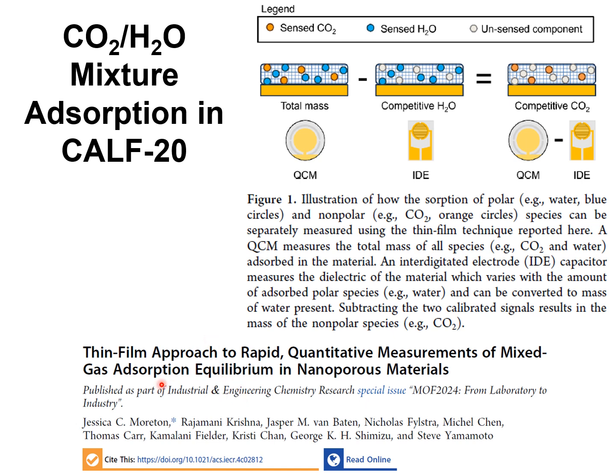This development is reported in the paper titled Thin Film Approach to Rapid Quantitative Measurements of Mixed Gas Adsorption Equilibrium in Nanoporous Materials. This paper is co-authored by researchers from Matrix Sensors and also researchers from the universities of Amsterdam and Calgary. The thin film approach was used to measure CO2-water mixture adsorption equilibrium in pristine CALF-20 materials.